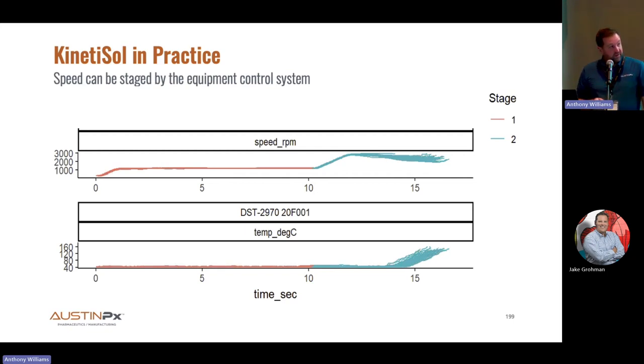And whether or not that kicks off at, I don't know, what is that, 11.2 seconds and 14 seconds? I mean, it's kind of funny. It's like plus or minus 2 seconds. Like, this is not relevant. What's relevant is that the shape of this curve and the endpoint of that curve and the speed is the same every time. And so this is that energy balance I'm talking about. As we're running the process, maybe it was a little hotter and kicked off earlier. Maybe we stopped the process or the first shot kicked off a little later, but this doesn't affect the quality of the system or the product that we're making.